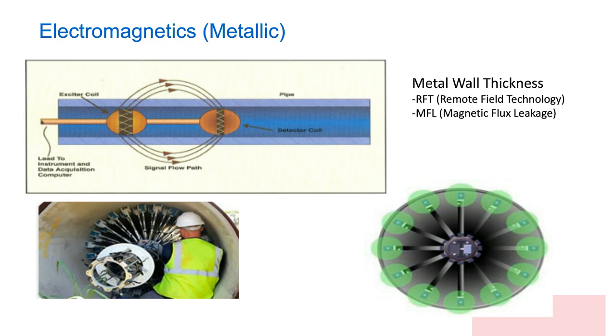And as we pass that magnetic field through, we're measuring any deviations or fluctuations within the magnetic flux lines. And if we have a solid pipe, in this particular case, as this instrument moves along the pipe, being typically pushed because these are large diameters, we see that because the wall thickness is the same, the magnetic flux or magnetic field doesn't change. But when we encounter pits or loss of metal, what happens is that the magnetic field changes. And it's the changes or the deviations in the magnetic field which is correlated back to the wall thickness of the pipe.